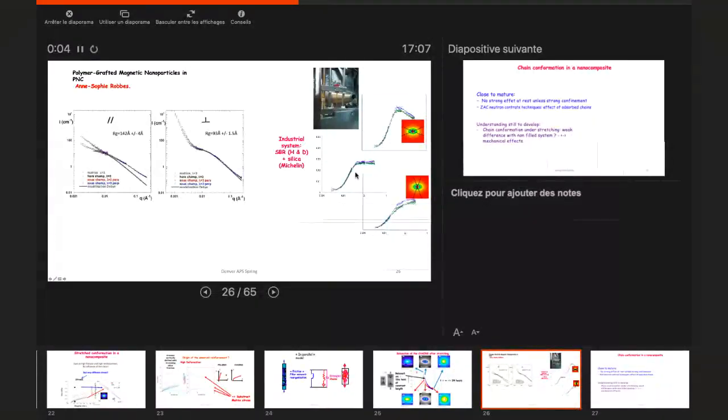Yes. On the right hand side, you have different scattering curves, which are not the form factor of the chains, but the form factor times the square of the scattering vector, q squared times S1 of q, which is the so-called Kratky plot versus q. It usually shows this initial increasing part and then a plateau due to the Gaussian chain conformation.